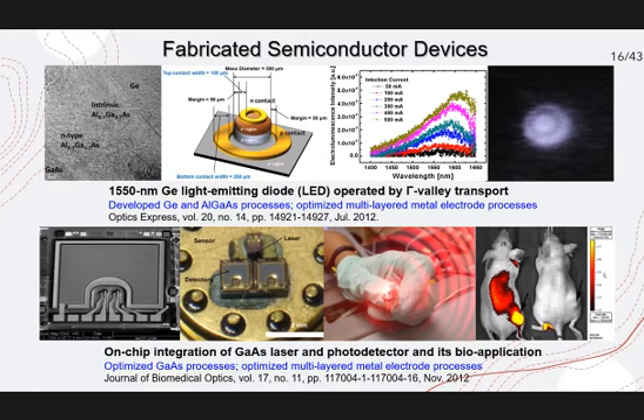So there should be a carrier source prepared for delivering carriers that can be combined with the waiting holes there. Aluminum gallium arsenide with 30% aluminum fraction was found to successfully transfer electrons from the gallium arsenide layer to the p-type germanium substrate, and emission of 1550 nanometer wavelength was obtained from the fabricated device. And on-chip integration of a gallium arsenide laser with a detector for a biosensor application. The device was evaluated as a biosensor in collaboration with the medical schools of Stanford University, UCLA, and University of Toronto. That was also a very interesting and fruitful time.